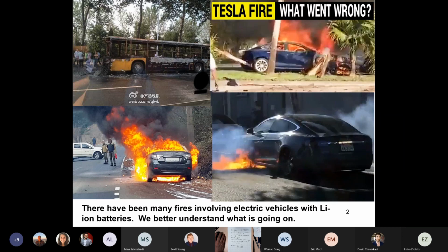Just to give you a feeling, when we had our issues at Moli Energy with lithium metal, molybdenum disulfide cells, we put 2 million cells into the field, and we had 10 safety incidents. Okay, that's 1 in 200,000 cells. How do you detect that at the experimental level? You think about it. Not easy to do, 1 in 200,000. At that time, we figured the safety had to be one incident in 200 million cells.